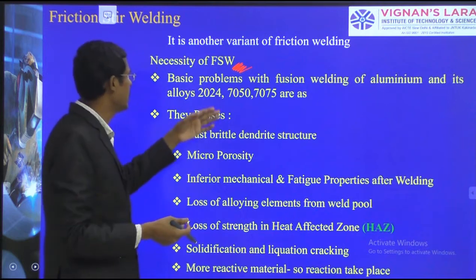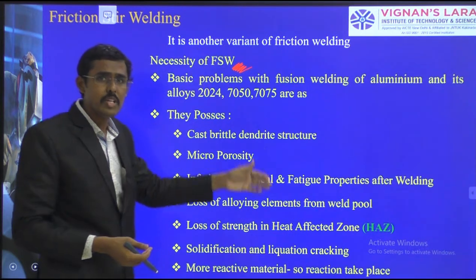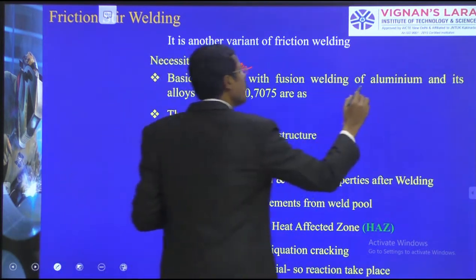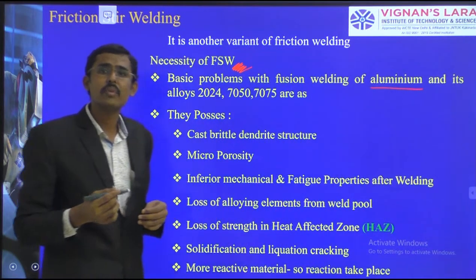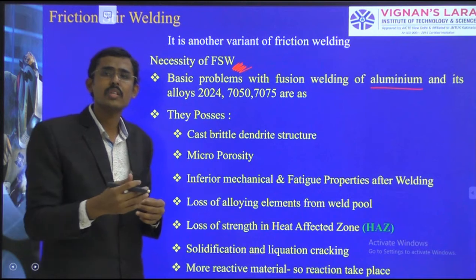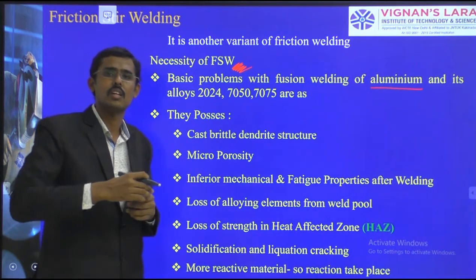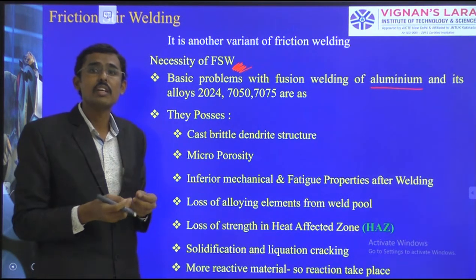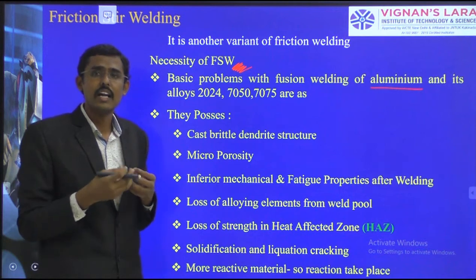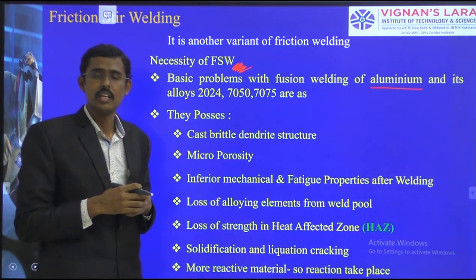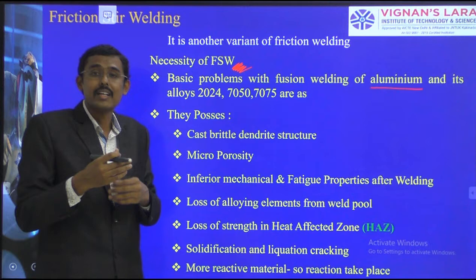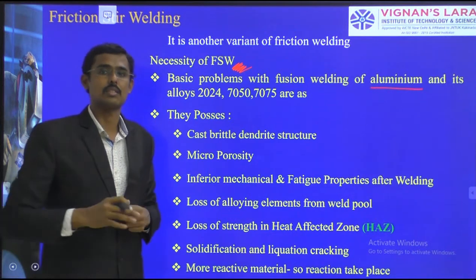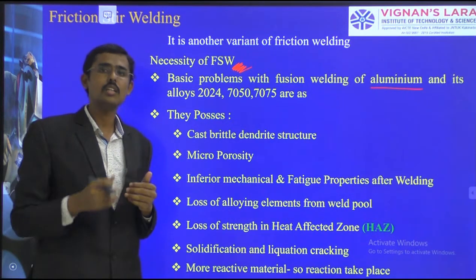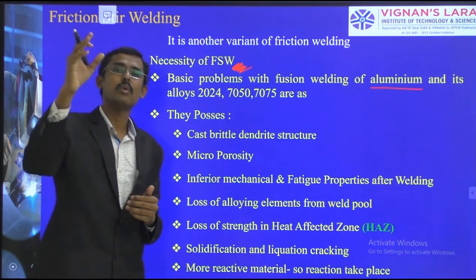Here, importantly, welding of aluminium is very difficult as it melts at a very low temperature, a melting point of around 600. It is difficult to generate heat, melt and solidify. In the meantime, microstructure changes also occur. Therefore, we should not reach the melting point of the material.